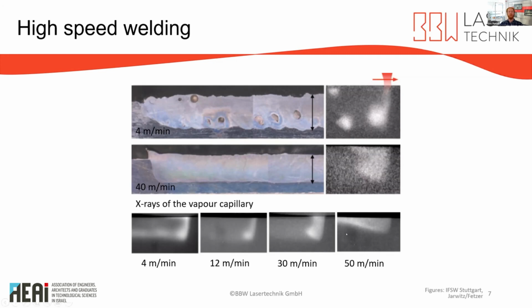So what was achieved here is nearly no pore generation, but there are other disadvantages at this speed. We go into a regime where humping effects occur. And there's also another disadvantage when we weld a material with a hot cracking tendency. We have the problem that the hot crack tendency increases mostly with higher welding speed.